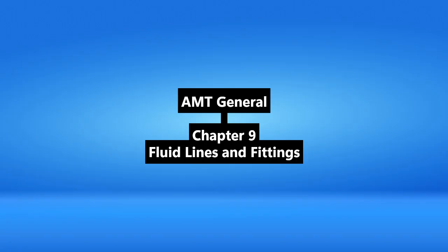Absolutely. No burrs. For softer metals like aluminum, copper, a standard tube cutter works well. Figure 9-2 shows the technique: rotate, gradually tighten the wheel. And for harder stuff, steel, titanium? The chapter mentions specialized chipless cutters, or even a fine-tooth hacksaw, like 32 teeth per inch, to get a clean cut. And getting rid of burrs afterwards is non-negotiable, inside and out.